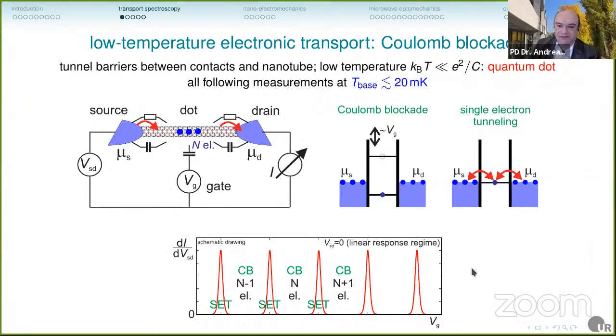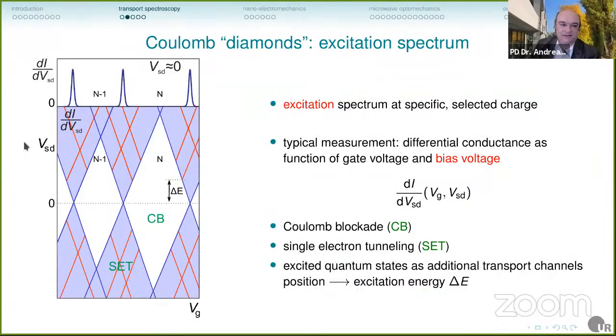Now, if you want to do spectroscopy, you can tune one more knob, and that is the source drain voltage, the voltage that is applied across the nanotube. And then these Coulomb oscillations, which correspond to the cut here at 0 source drain voltage. This is the cut here. They expand into finite regions of current. And these regions, they are not featureless. They have steps in the current corresponding to resonances or to lines in the differential conductance. And these lines correspond to excited quantum states of the trapped electronic system. And from their positions, for example, we can directly read out the excitation energies.